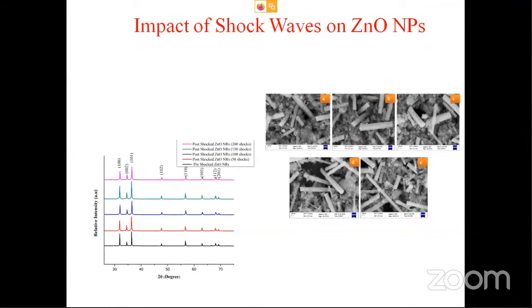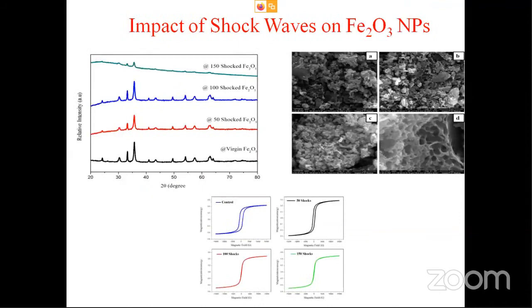For this material, you can see we have given shock. This is the control, 50 shocks, 100 shocks, and 150 shocks. You can see the XRD pattern is almost the same, but the magnetic properties are changing. And the morphology, you can see, is an irregular pattern in the control, and this is 50 shocks, 100 shocks, 150 shocks. You can see the morphology is completely changed. Due to this morphology change, the magnetic properties also changed.